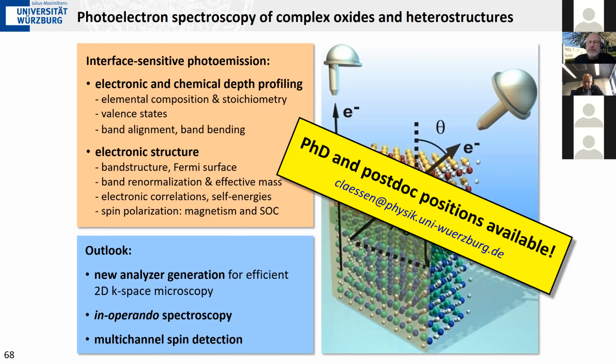And some of the oxygen comes from the residual gas in your system and oxidizes the surface. And that's the picture. I'm not quite sure if that's a model, but if you want to understand where your off-stoichiometry comes from, you have to change the conditions at the interface. That you do by changing the substrates, and you have to change the conditions at the surface by either capping the surface or looking at the surface profile. Not sure if that answers your question.